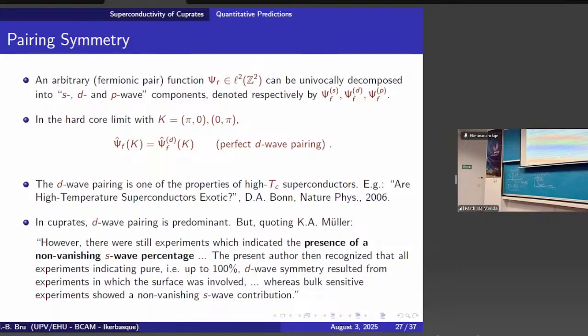Maybe it's a lot of information for physics, but the cuprate also has a very particular property with respect to conventional superconductors. You have a macroscopic superconducting state, and in conventional superconductors, typically this macroscopic wave is isometric. It's a so-called S wave. But for cuprates, there is a D wave part, a significant D wave part. D wave part means that the wave function, when we make a 90 degree rotation, you get a minus sign.